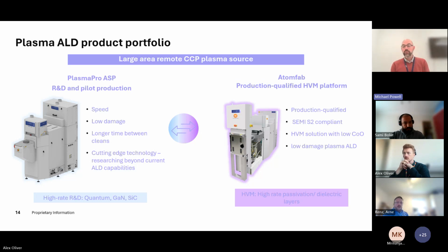If we switch over to atomic layer deposition, we have an ability to deposit a gate oxide and to reduce some of the contamination and some of those species that cause issues at the interface, because we aren't generating so much carbon there. Within our portfolio, we have two systems that allow us to develop ALD for R&D applications and HVM applications. They're based on a broadly similar level of technology as well. So if we generate something on our PlasmaPro ASP platform, we can actually transition it to high volume manufacturing quite quickly, because we're not talking about a fundamentally different plasma source, or a fundamentally different way of depositing the material. What we're talking about is taking something that works well at an R&D level and making it applicable for high volume manufacturing, so it has the right certification, and then we can show the CPK and the marathon trials that will give you the long-term control over that as well. Next slide, please.